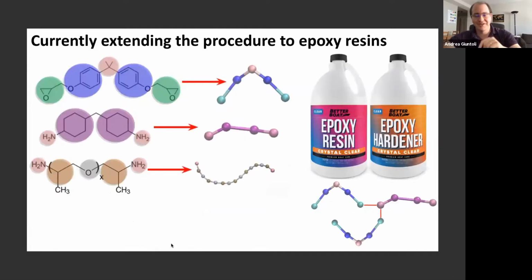And I'm currently using these ideas to create a model for even more complicated systems, in particular for epoxy resins. Systems in which you typically have two different molecules. One is the resin and the other one is a hardener component that is able to create links with the resin and to create a polymer network. And we are now creating a coarse-grained model of this kind of system using this recalibration approach.